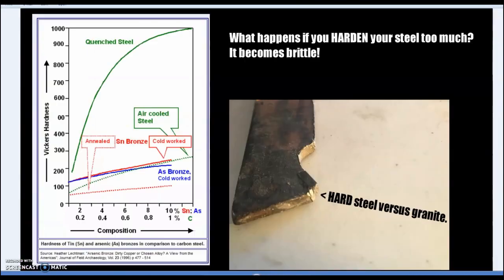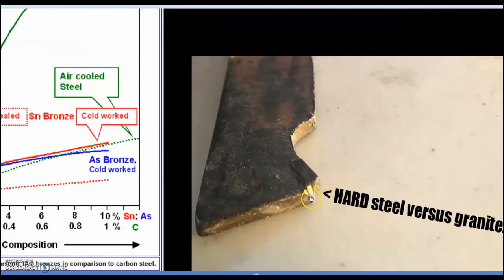Now it's important to note. So now we see that same line again, but then we look at quench steel. Look what happens when you quench steel. It gets really, really hard really quickly. But what happens if you use super hard steel, like high carbon or quench steel? When you harden it too much, it becomes brittle. And here's an example, and I'll show you a video. The first time I did it by accident, so I filmed it and ruined my tool the second time. But this is what happens when you use hard steel versus granite.